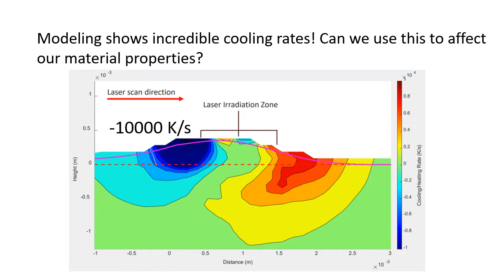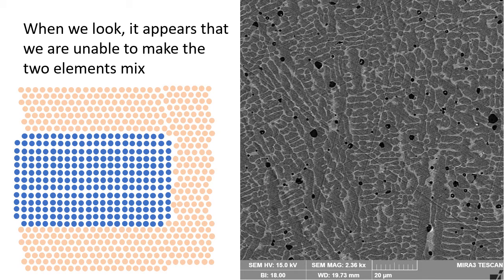And because laser additive manufacturing has a nifty property of incredibly high cooling rates, we were wondering if these super high cooling rates would actually freeze the copper and iron together in a new novel alloyed structure which we had never seen before. Looking at the microstructure of these samples after we printed them, we saw that there was still separation between the copper and the iron, with the copper here being shown as the lighter phase and that darker phase being the iron in between. It appears then that we weren't successful in actually getting these two elements to mix at the atomic level, even though we have a very fine mixing at the microscopic level.